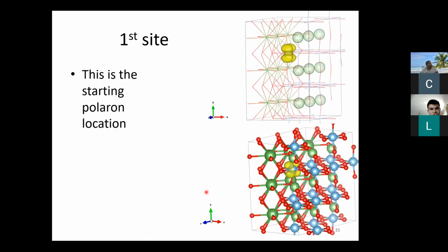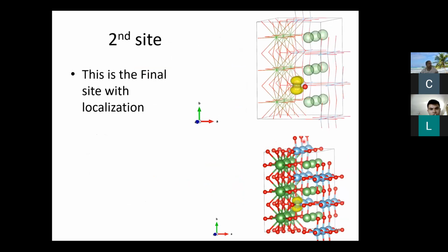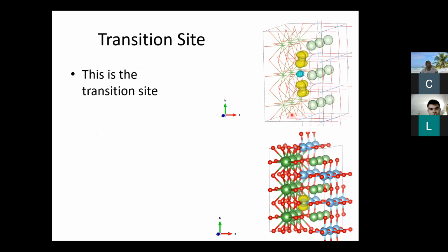The first site was just here on this one site. The next one was on the bottom. So these two are just different sites, and this is the intermediate state that I got. What's pretty interesting is that you can again see a D-shaped orbital here. And in the oxygen, since it's overlapping and there's a partial occupation of this charge density, you can see almost a p orbital here. I thought this was pretty neat, getting to see some of the orbital interactions of chemistry or quantum physics in here.